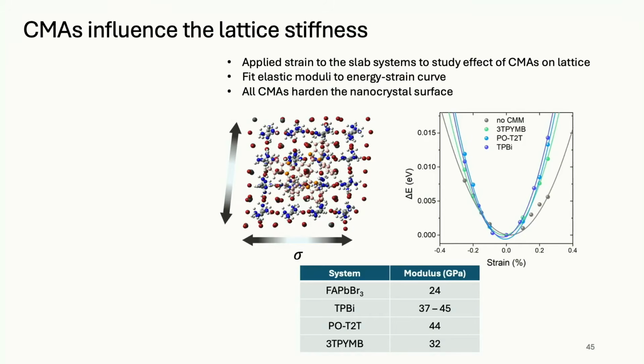First we showed, if you take this material and then you put these molecules on and you ask how stiff is the material, we calculate the energy versus deformation. If you don't have these molecules, here is the parabola of energy versus strain, but all of the molecules stiffen it. Can you see that? So back to the mechanics idea. From a mechanical point of view, it's literally making it stiffer by having a multi-point ligand.